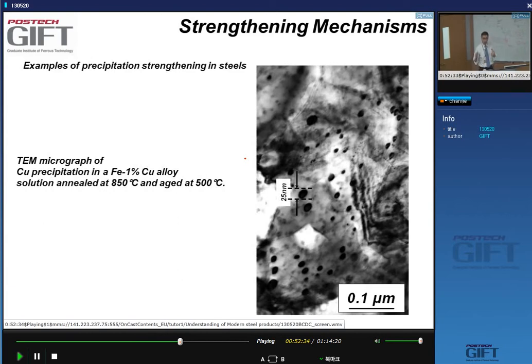Are there systems where we strengthen steels using precipitation hardening and we don't have the Orowan looping mechanism? Yes, you can harden steels, ferritic steels, with copper, and get very tiny coherent precipitates of copper in your iron matrix. So here you can see a grain, it's in TEM, very small particles are present in the ferrite matrix. This is copper, yes?